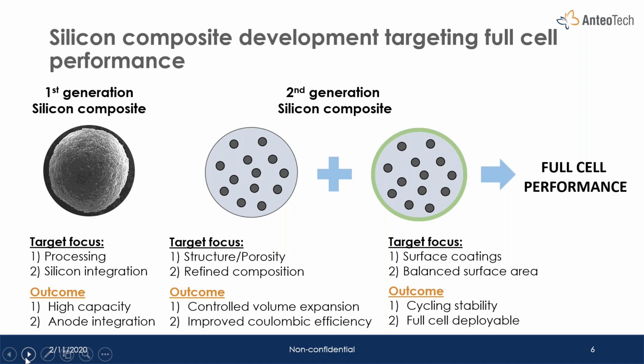The next challenge that we are undertaking is to try and control the expansion of the silicon within that silicon composite, and therefore improve the cycling stability. Now, this is a problem that has beset the entire industry, the problem of silicon expanding and therefore lowering the cycle stability of the anode. But we've progressed quite well in this area, and we're starting to see some really good results. Perhaps, Manuel, you can talk us through the process and what we're achieving there.